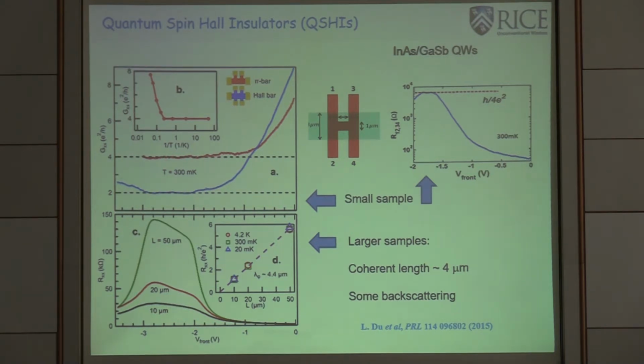Now, what's the reason for this? We're going to mention later, but just from the experimental point of view, you have two regions. You have a small sample, you see the quantized transport. If you go to a sample size larger than a certain characteristic length, you end up with non-quantized edge transport. Okay. So what is this characteristic length?